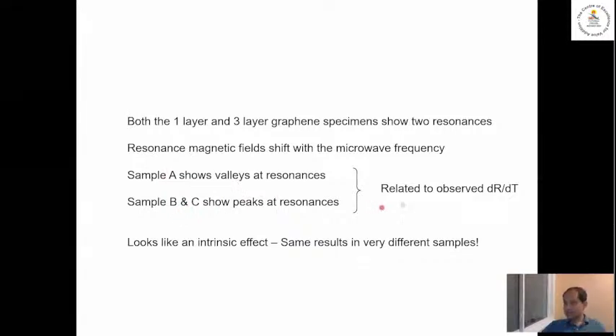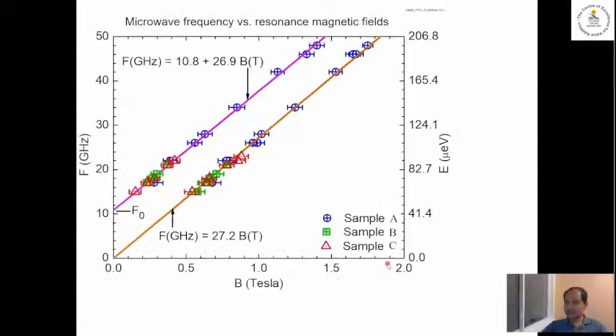But this could be understood. Whether you see a valley or a peak depends on how the resistance changes with temperature. If the resistance increases as you increase the temperature, then you get a valley at resonance. If the resistance decreases when you increase the temperature, then you get peaks at resonance. Okay, so now let's summarize our results.